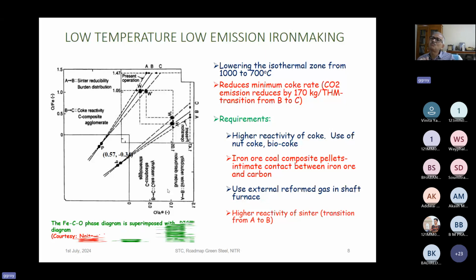That means you can utilize only 30% of the CO. And this is called the CO utilization. This CO utilization decreases even further at high temperature. But if you can reduce the temperature, then your CO utilization increases. That is basically the essence of this method. If you can reduce the temperature of the isothermal zone, where the majority of the indirect reduction, FeO to Fe, takes place, from 1000 degrees centigrade to 800 or 700 degrees centigrade, then you can increase the CO utilization. As you increase the CO utilization, obviously the carbon efficiency of the blast furnace increases.